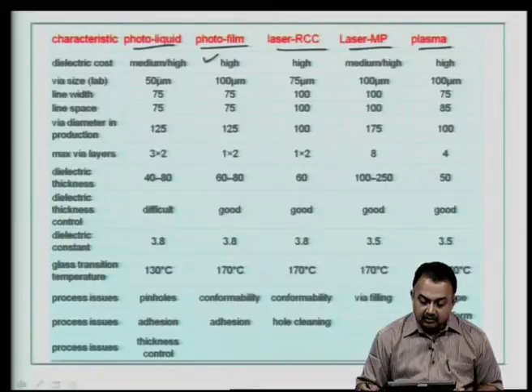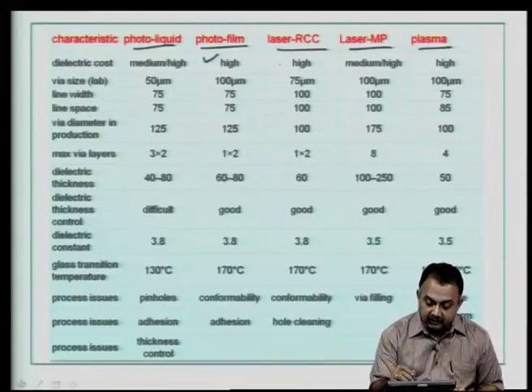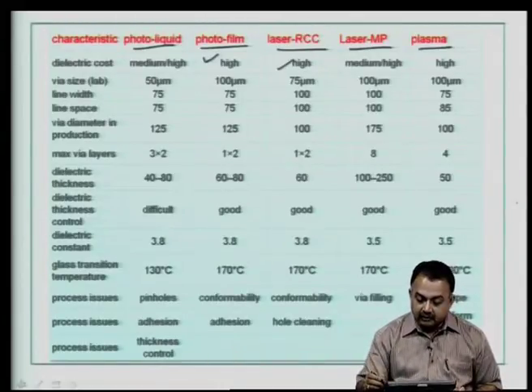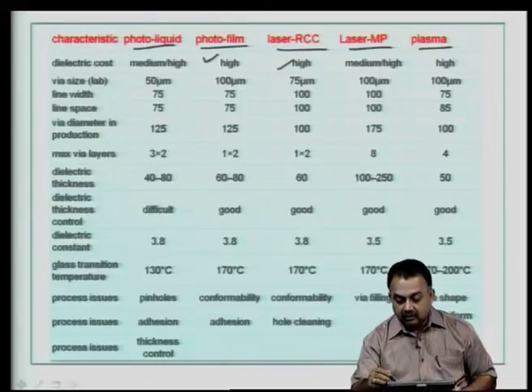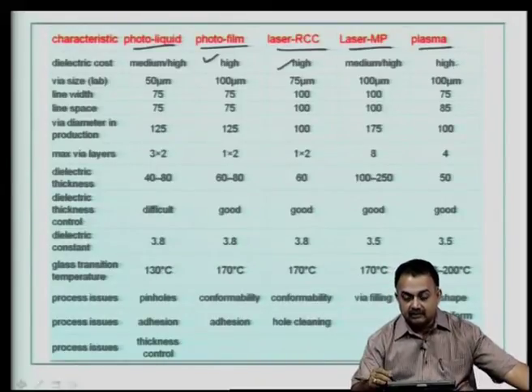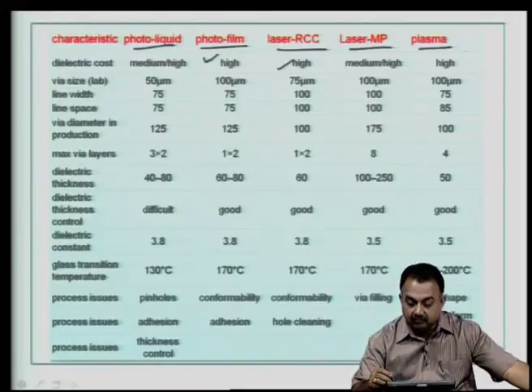Now, the resin coated copper foil is readily available and compatible with the laser drilling, the cost is fairly high. And then plasma, because it is also fairly a parallel process, but again depending on the thickness of the material that needs to be etched, it can be time consuming. Therefore, manufacturing wise it is a costly process.